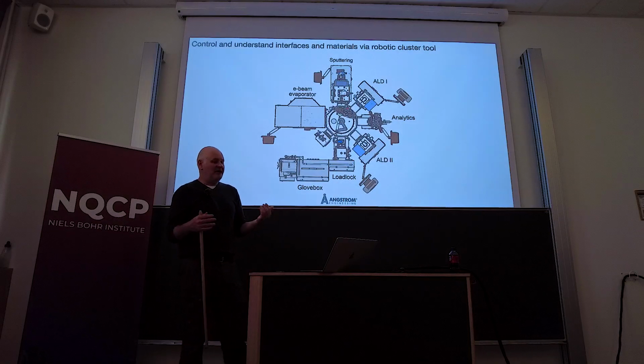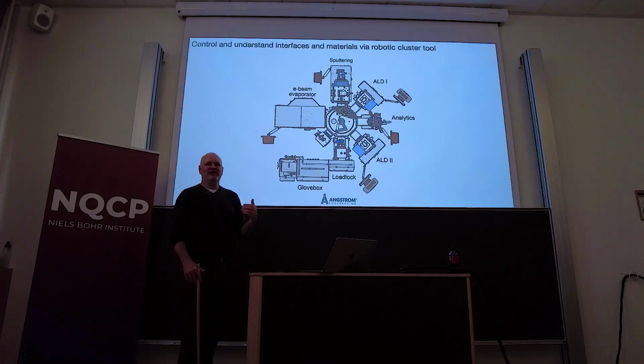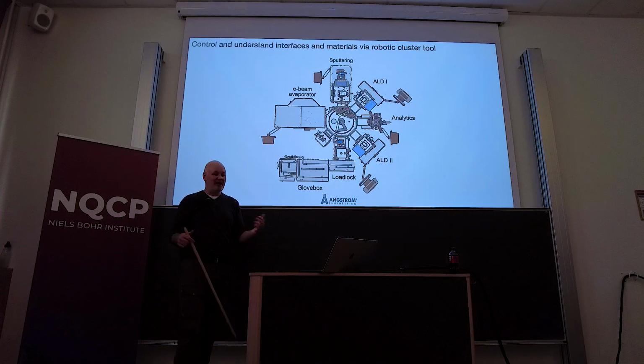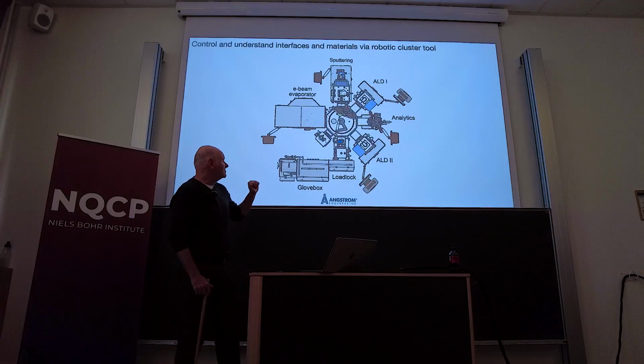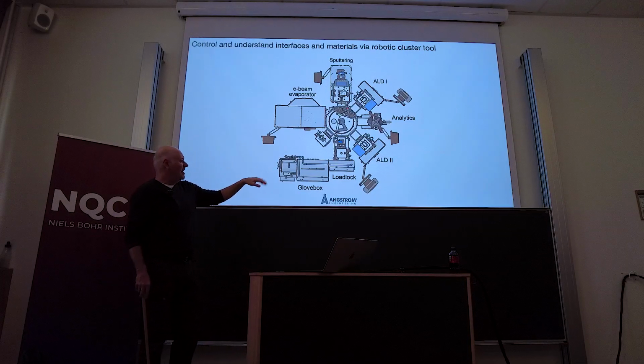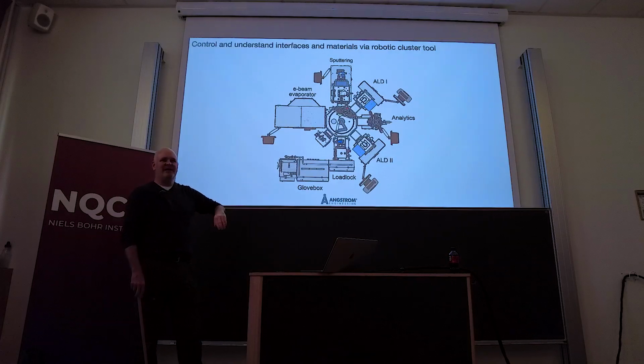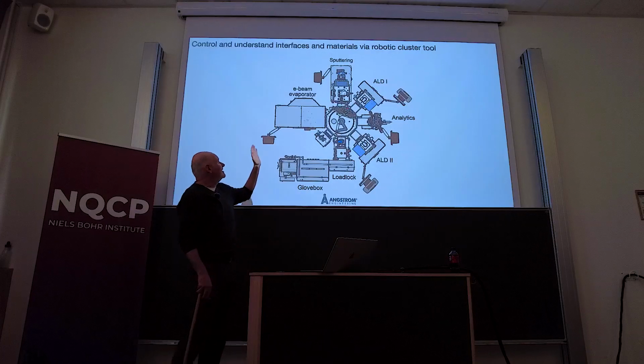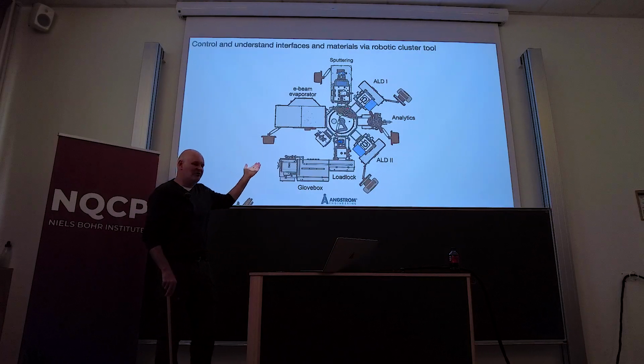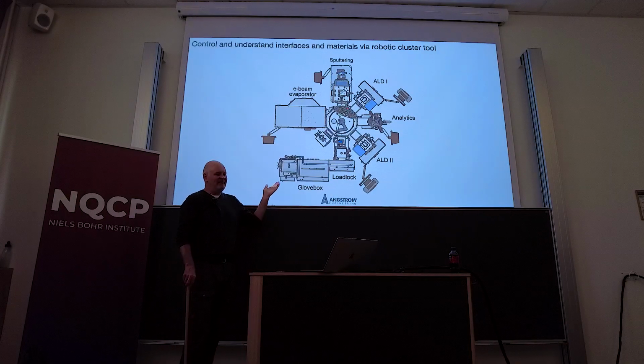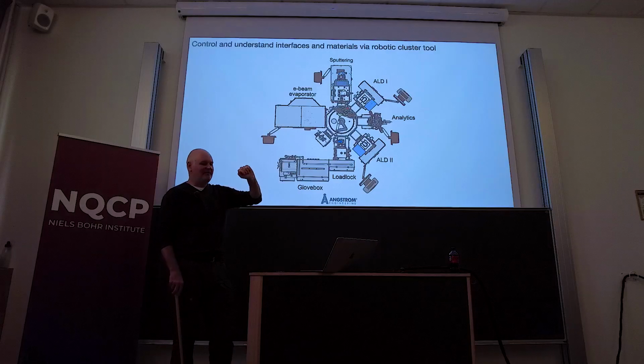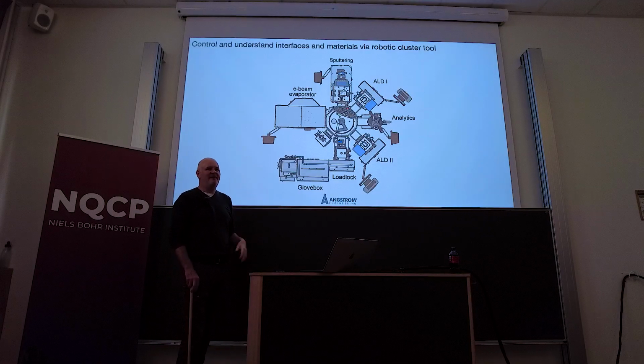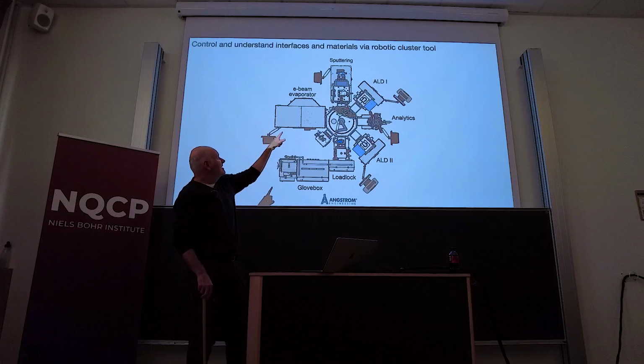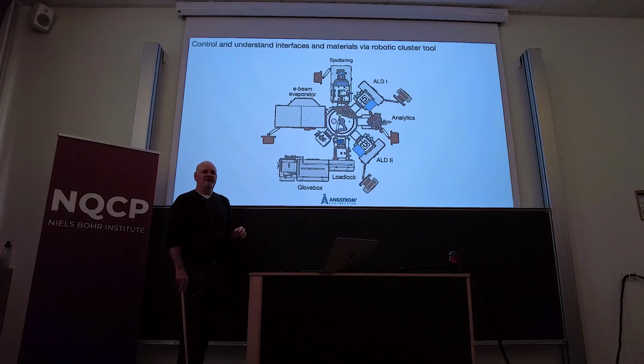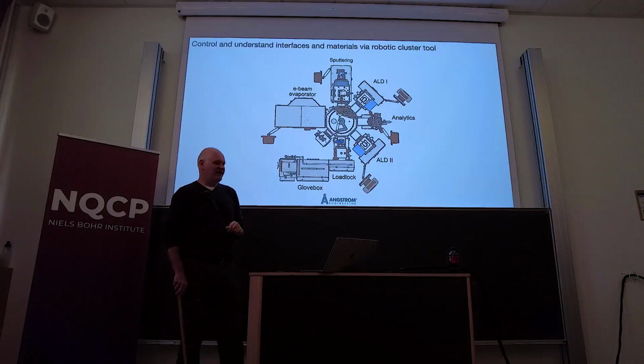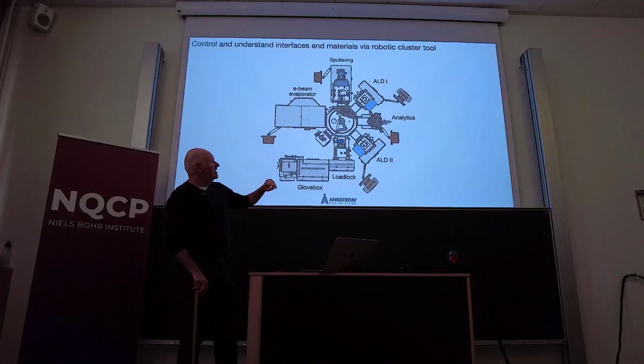but grow new things, but also make sure that we can make devices that are at least as good as the standard qubit device made out of aluminum and niobium. And so what we built was this tool here. It has a load lock that can basically load in 10 wafers at a time, so we can do some automation with this. We have an e-beam evaporator, which they call the quantum tool, but it's a Josephson junction making machine. It's an e-beam evaporator that has rotating and tilting sample holder so that we can do conventional JJ fab with aluminum. Then we have a sputtering chamber at the top. That's reactive sputtering. So the plan for this was to do nitrides, and I'll talk a little bit more about nitrides in a bit. And then 2 ALDs, so atomic layer deposition systems.